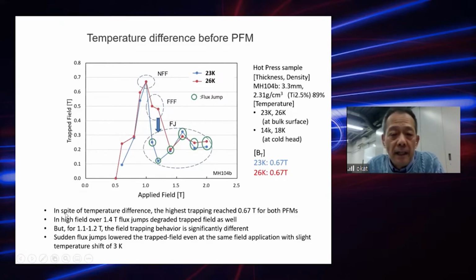So then we take just one sample, and the temperature difference between before PFM was estimated. In spite of the temperature difference of 23 Kelvin and 26 Kelvin, this is just a little difference between the sample temperatures. These are the 14 and 18 is the cold head temperature, so that is reflected like this. So in spite of the temperature difference like this, the total overview is quite similar.